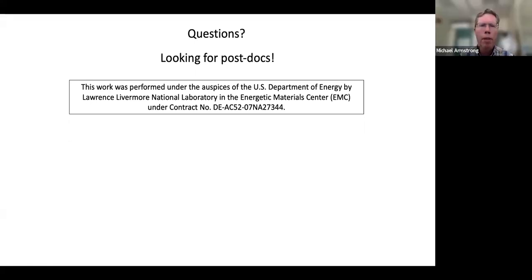Our target was basically 100 GPa in the aluminum. The reason was that we wanted to get to a pressure above where people had seen transformation of diamond in the past. In shock experiments, most people know that where you see this transformation occur depends very strongly on how fast you compress.